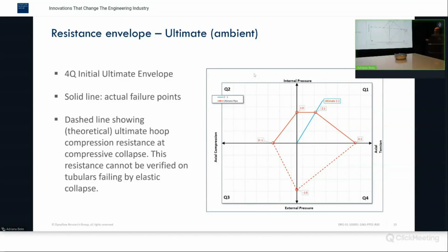From the ISO 14692, we used to work with an internal pressure test. So that is at ambient conditions, and that delivers this point in this quadrant, the Q1. From that the 1.0 is derived, at the same internal pressure level. So the difference is the way in testing. So you have with an end cap, without an end cap. The 0, 1 is the actual tensile ultimate, and the 0, -1 is the compression ultimate.